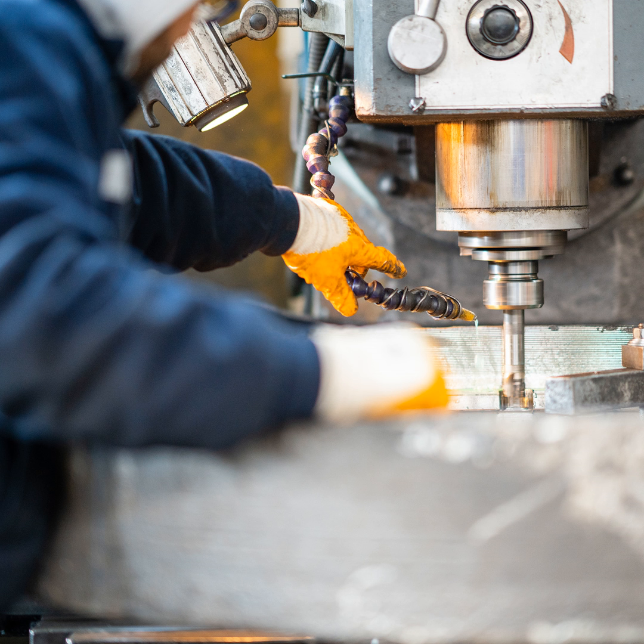Here are some typical speeds and feeds that I made for the ISO S class. ISO S3, which would be nickel-based alloys, for example, Hastelloy, Inconel, Incoloy, Monel, Waspaloy, and such. The ISO S titanium alloy, commonly 6AL4V. If we look at some of the feed rates here, for titanium we're looking at 2 thou to 2.5 thou feed per tooth, running that around 100 to 120 SFM. We do have some real world results from an aerospace engine manufacturer. This was a helical ramp mill, a series of 18 holes per part in 718 Inco.